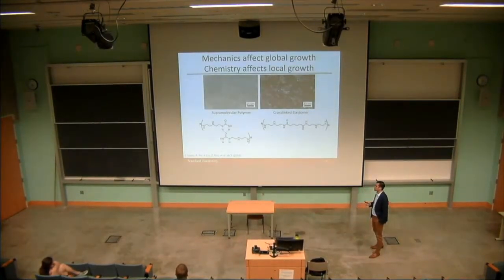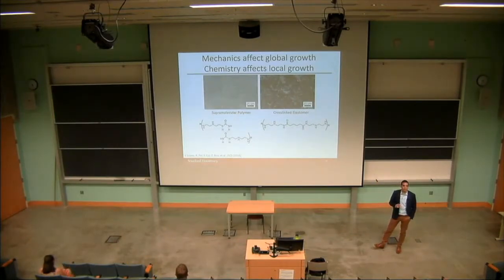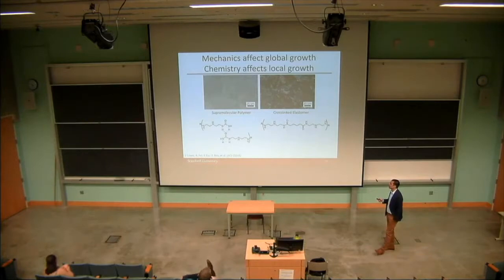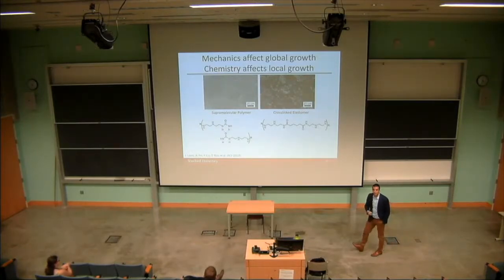And where we started was just back at the self-healing polymer, but understanding the mechanics. So I mentioned before, mechanics are thought to be very important for this lithium metal interface. And so what we did was take this supramolecular hydrogen bonding self-healing polymer and covalently cross-link it here. Instead of the hydrogen bonds, it now has a covalent link, and now it's an elastomer. So instead of a viscoelastic flowable material, it's just a thermoset.